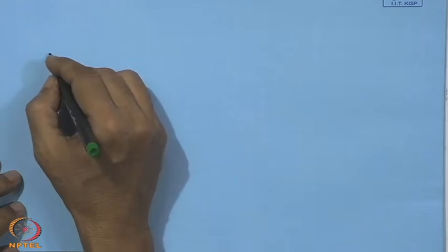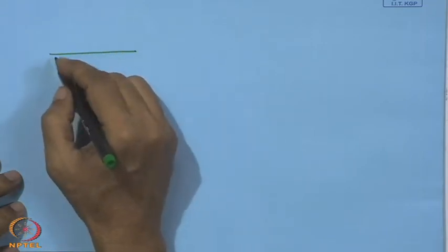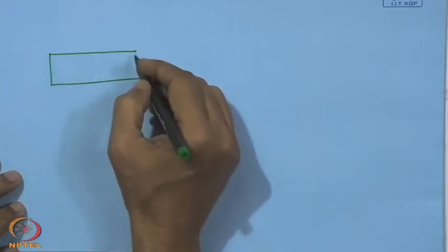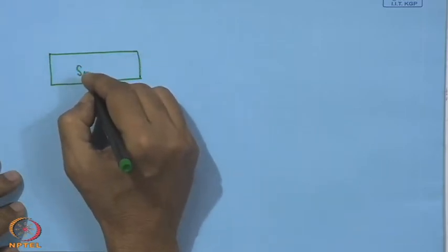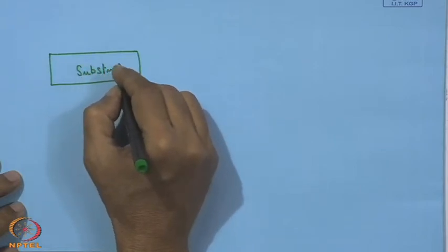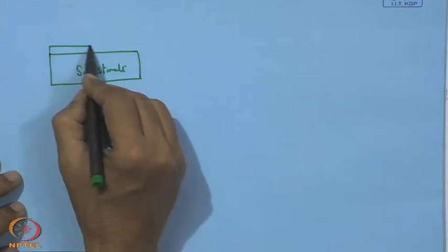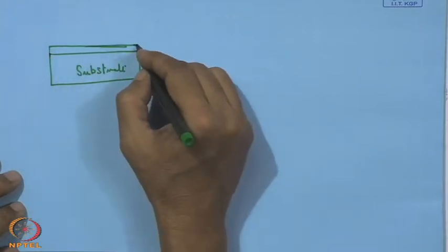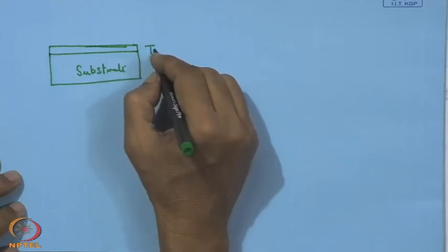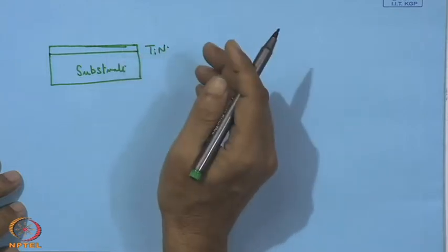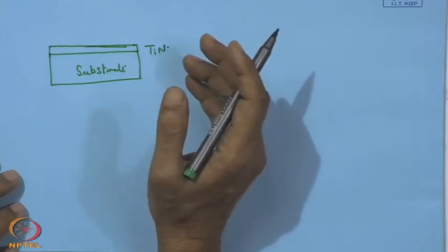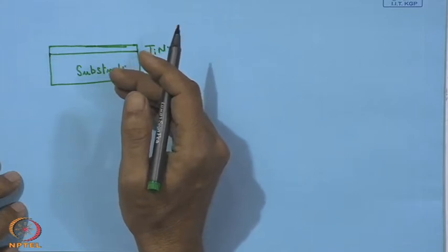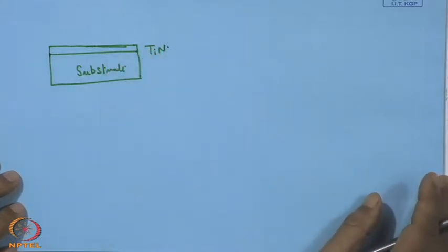We can have another architecture, that is, say for example, it is also known that if this is the substrate, then over this substrate we can build a titanium nitride coating. There is no difficulty in getting a titanium nitride coating. So, titanium nitride by reactive sputtering, by using a DC or RF or pulse DC, that can be very well used. However, the whole idea here is to improve the performance of MoS2.